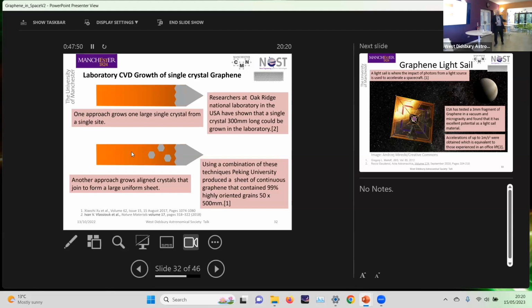But another approach is to say, well, that copper is all higgledy-piggledy itself. Those atoms are all over the place. Why don't we anneal the copper very carefully so that all the atoms are lined up in the copper, so that the carbon atoms in the graphene have nice, comfortable places to sit on top, and all these different islands will grow in the same aligned manner? So that's the second approach.